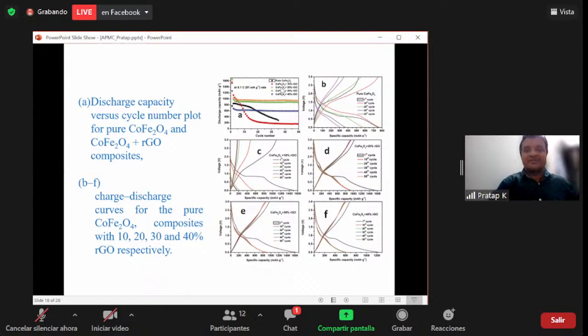So look at the orange one, cobalt ferrite with 20%. It is showing a capacity of 1000, and even after 50 cycles, it is stable, meaning it is not leaking. It is regaining its own capacity, and it is really good. That is why we are using this cobalt ferrite with 20% RGO. These are the charge-discharge curves for pure cobalt ferrite, 10% RGO, 20%, 30%, and 40%.